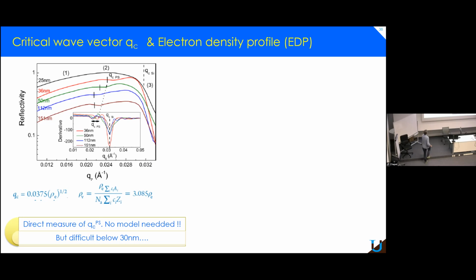What I'm saying here is that at least for the thickness above 20 nanometers, we were able to directly measure electronic density that was higher and higher with the thickness. But I agree that we would like to make a rougher substrate to see the influence on the actual density.